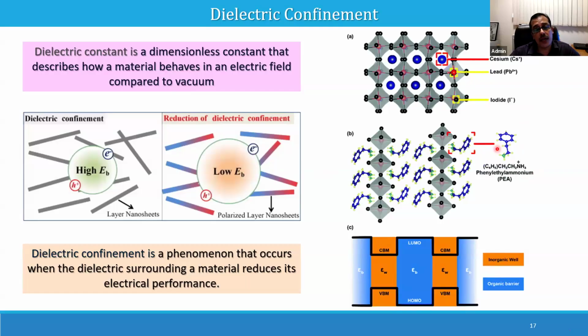Okay, so in addition to quantum confinement, there is dielectric confinement, because there is a dielectric difference between the inorganic component and the organic component. For the inorganic, the dielectric constant is high, and for the organic, the dielectric constant is low, because the polarizability is poor for the organic part. So one is high and one is low, and that is actually a confinement. Just like quantum confinement, here is dielectric confinement. So if you use a polarizable organic cation, you can actually reduce this difference. Okay, so you can bring the dielectric constant closer to the inorganic structures, and that can reduce the dielectric confinement. So that is our next target.